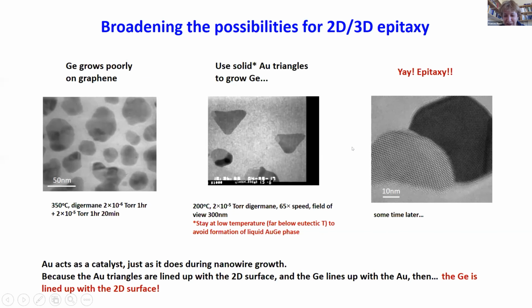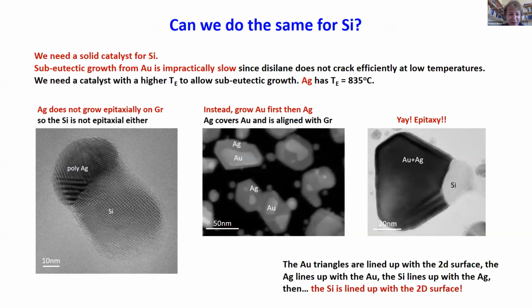So it's like a chain of epitaxy, a transfer of epitaxy, and we can do the same thing with silicon. We use silver as the catalyst, but we have to anchor the silver onto the graphene by using some gold. So now we have an even longer chain: graphene, gold, silver, and then silicon. So it may not be practical, but it's kind of fun to see all these crystal structures following each other in terms of their orientation.